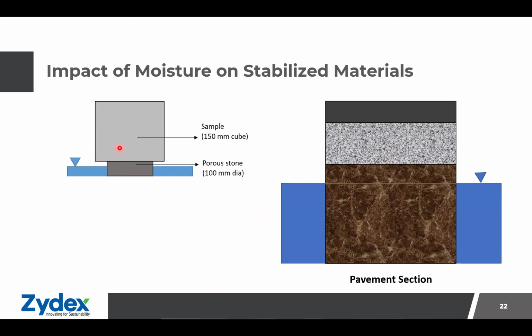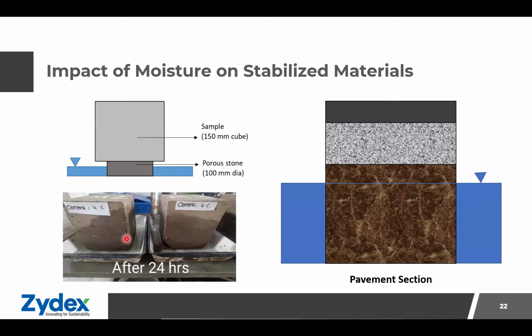condition can be simulated in our lab by just keeping a cube sample on a porous stone, which is submerged under water. Now, since this is a soil plus aggregate mixture, it has a tendency to absorb water. This absorption of water leads to further issues and water-related damages. So this is one of the pictorial views from our experiments that we are doing.